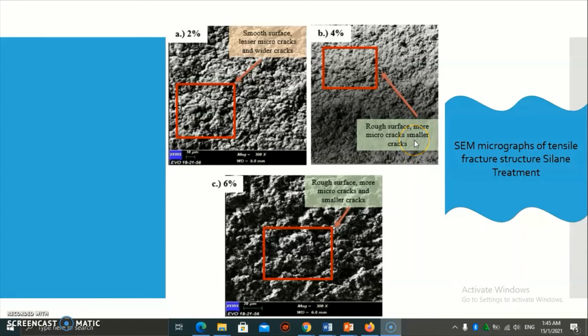Okay, this figure is for the same micrograph of tensile fracture structure with silane treatment. This part is the 2% silane treatment, where, as you can see here, there is a smooth surface, less micro crack, and wider crack. For the 4%, the surface was rough, with more micro cracks and smaller cracks. Okay, for the 6%, the surface was rough, with more micro cracks and smaller cracks.